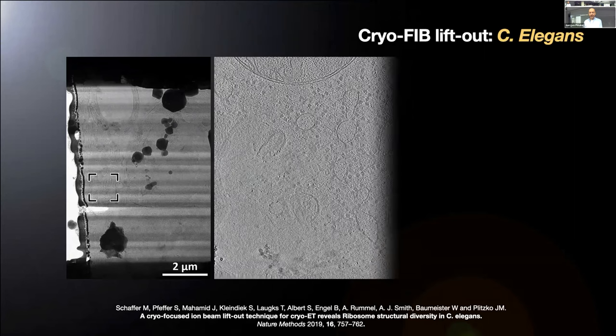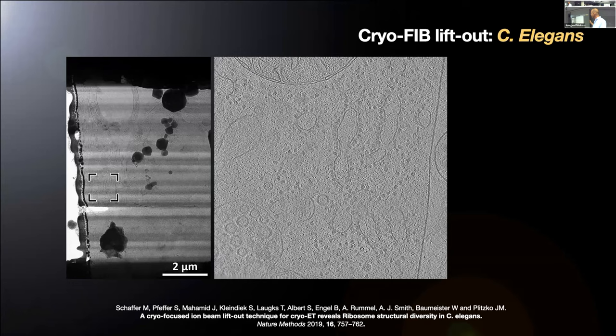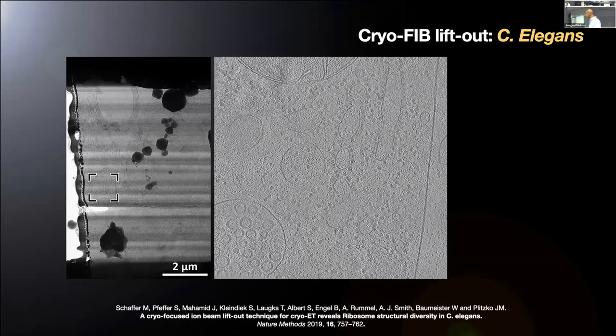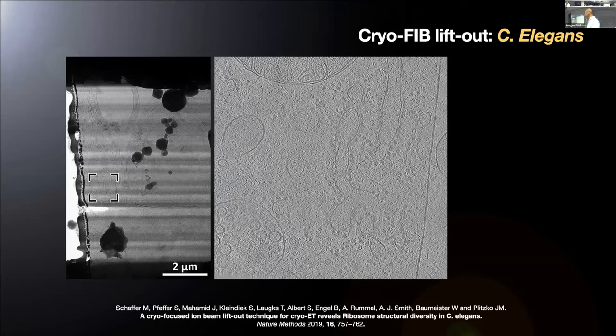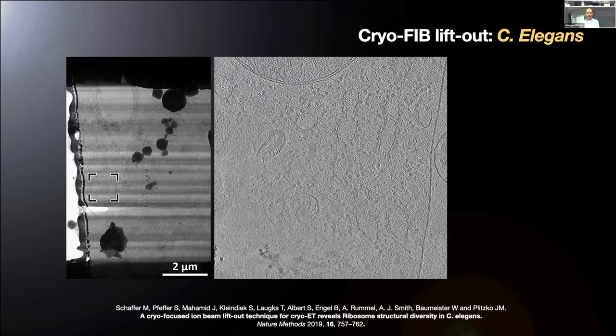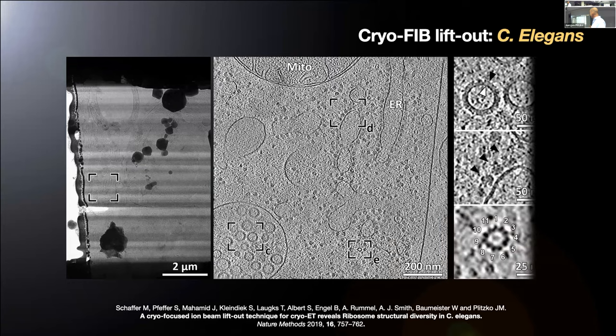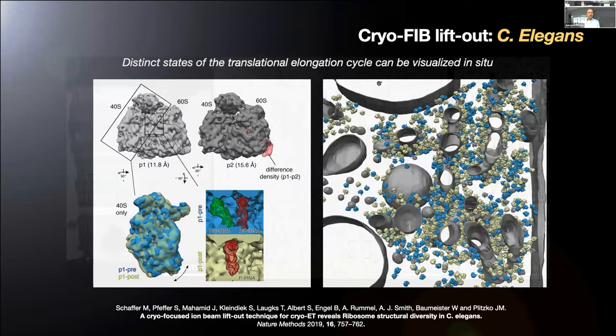And we took a couple of tomograms, and we were astonished about the quality. You can see that movie, you see the ribosomes, you see even COPI and COPII coated particles. You see a lot of structures, which we only analyzed partially. But what was fascinating is we just took the ribosomes in different parts of that organism out of these tomograms, which we took only five, and we analyzed their conformational states. And we found out that they have distinct states at a resolution of 15 angstroms, approximately.